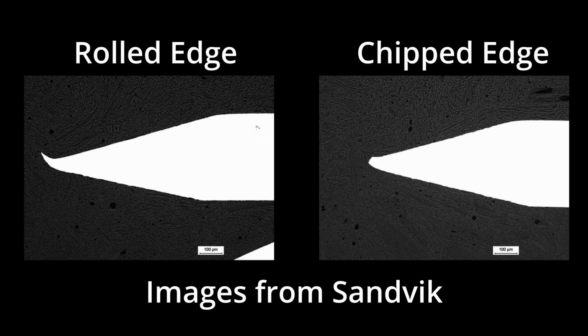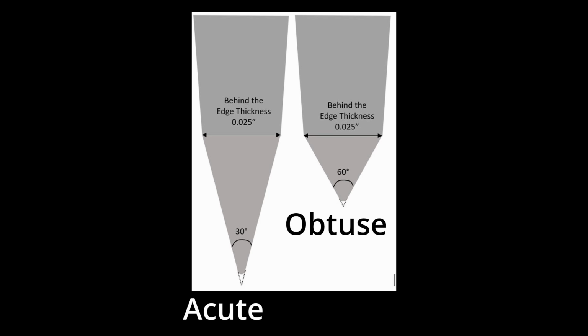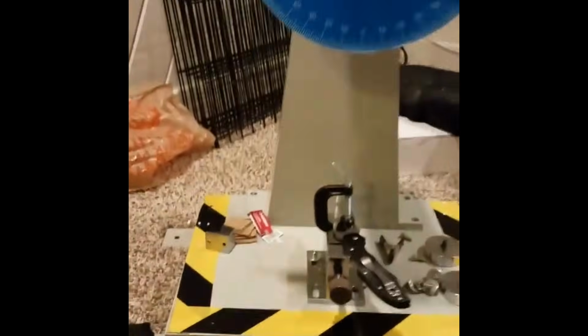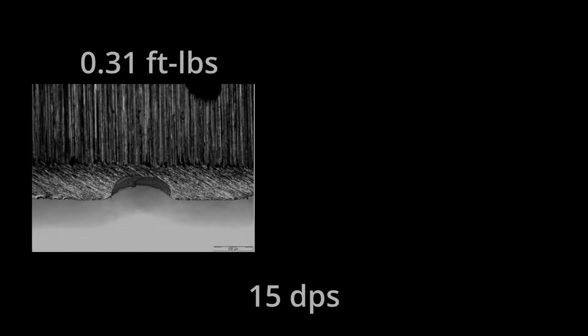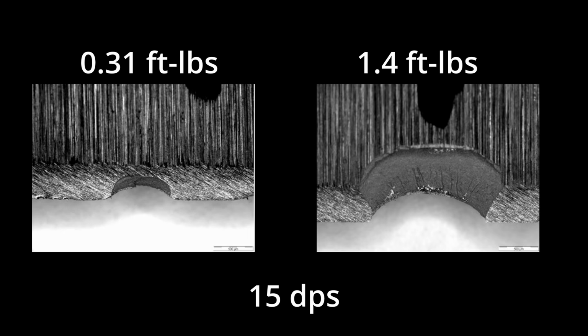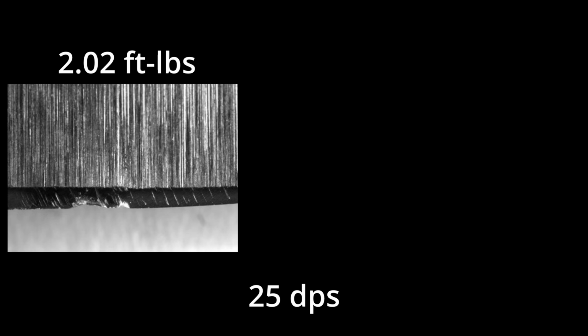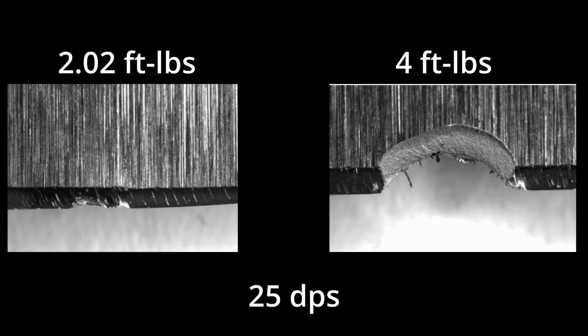Which leads me to the subject of edge geometry. If your knife is seeing deformation or microchipping, you need to sharpen it with a more obtuse angle. This gives the knife better resistance to deformation and microchipping by giving it a more robust edge. In a test I did on AEBL knives, I impacted them with a steel rod at different energy levels, from a gentle tap to a loud smack. With an edge sharpened to 15 degrees per side, only 0.31 foot-pounds led to a significant chip in the edge, and 1.4 foot-pounds was so severe that the chip exceeded the size of the edge bevel, at which point the chipping is catastrophic. With an edge sharpened at 25 degrees per side, 2 foot-pounds led to only minor rippling of the edge and needed 4 foot-pounds for catastrophic chipping.